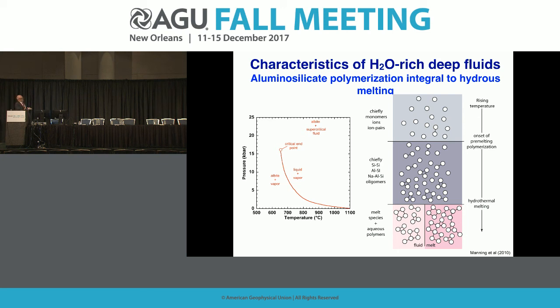Eventually, you have this reaction boundary here, and if fluid's present, it will be even more polymerized, but certainly the polymerized phase that's present after this is the melt. Hydrous melting can be seen essentially as a condensation reaction of the polymeric solutes that are dissolved in the aqueous phase.